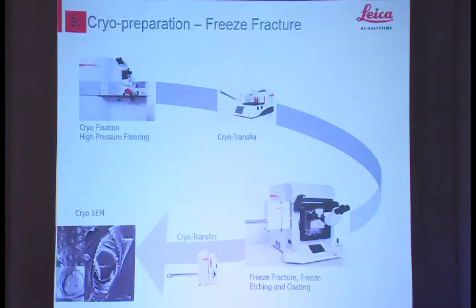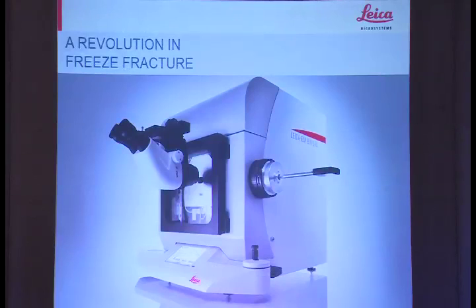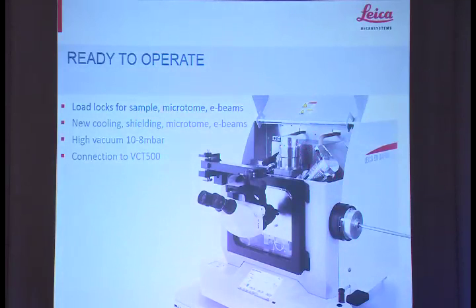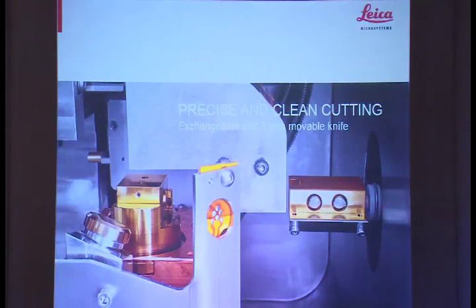And this cryopreparation freeze-fracture pathway is very useful for getting a different view on the world. Instead of looking at a slice of a sample, you can freeze cells and break them open, and the fracture follows the line of least resistance, which is through the membranes. And we have an instrument called the ACE 900, which is a new freeze-fracture device, which has been built specifically for this. So we can freeze our sample and then take it under special conditions into the freeze-fracture device, where with the help of E-beams here, we can coat the sample. So we can break it open, and inside the chamber there is a knife, so we can split open the sample, which would be sitting on this surface here, and break it open and then coat the sample.